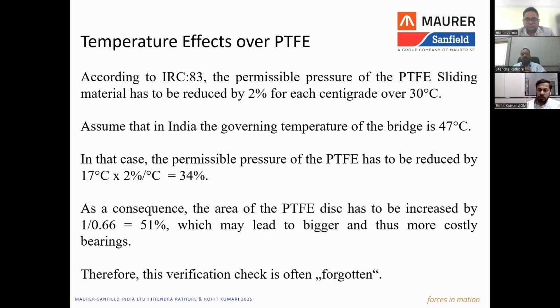The same applies in colder weather. In extreme cold, if you accidentally touch a steel surface, you feel a lot of cold, because the temperature of the material moves differently compared to air or environment temperature. So when you have steel bearings in railway bridges directly exposed to very hot temperature, the temperature in the sliding material, which is directly in contact with the steel plate, can go very high. And it is a clear caution mentioned in the code that PTFE cannot be used for any temperature exposure of more than 48 degrees centigrade. This is a very important point to understand. So we have to check this condition.